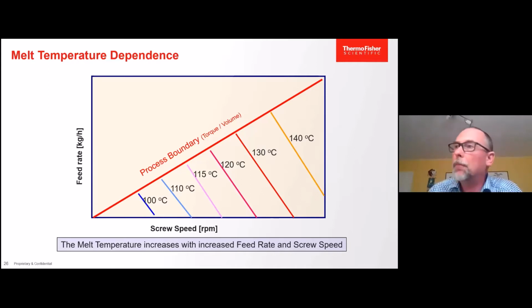Or the boundary might be torque, for difficult materials with high strength, high tensile materials which are difficult to melt, for example. And we see with increasing screw speed, we have here isothermal lines. So with higher screw speed, the temperature will also increase.